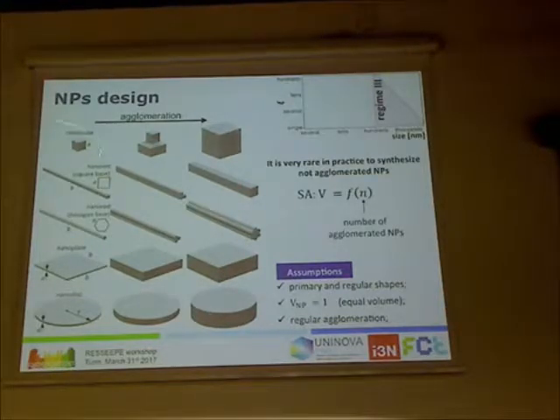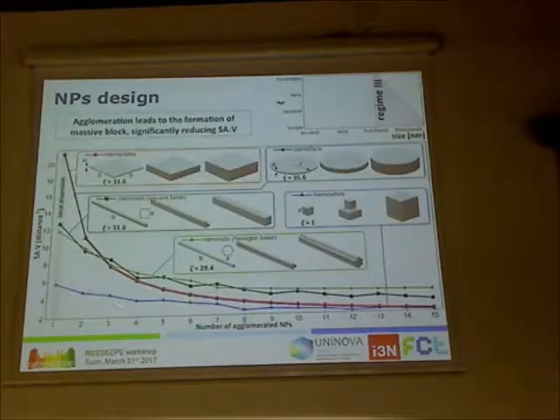That is the less advantageous particle if you consider the surface area over volume ratio. So in this regime where you start to have aggregation, it's important to see how this ratio of area available over the volume of the particle increases with the number of agglomerated nanoparticles. We see that nanoplates are very nice if you have isolated particles, but as soon as you start to have some aggregation, this ratio decreases a lot.